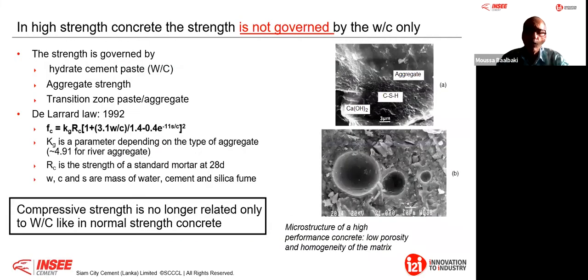Now, when we come to high performance, high strength concrete, this strength is not governed by the water cement ratio anymore. Here the limiting factor could be the aggregate, because to improve, you have to control the water cement ratio and you need to have a good aggregate. That is why, if you remember the last webinar on ultra high performance concrete, the way to do it is that the inclusion of coarse aggregate is omitted in the mix design. We just take it out. Otherwise, if you want to develop concrete up to 100 megapascal, you need to consider the role of aggregate, because the compressive strength is no longer related only to the water cement ratio like in normal concrete.